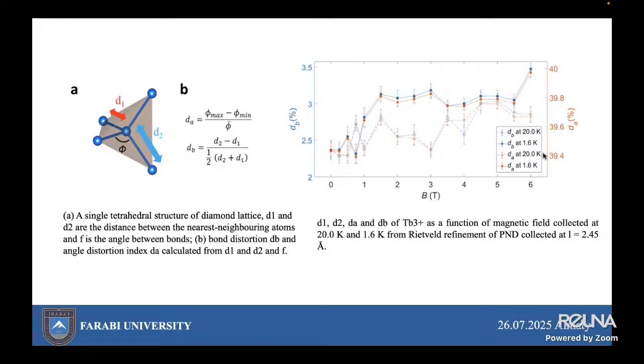In this research, we investigated terbium tantalate using magnetometry, heat capacity and neutron diffraction, revealing three-dimensional antiferromagnetic ordering at Néel temperature 2.25 Kelvin, confirmed by sharp transitions in the derivative of the magnetic susceptibility, the derivative of the magnetization by the intensity of magnetic field, and the specific heat.